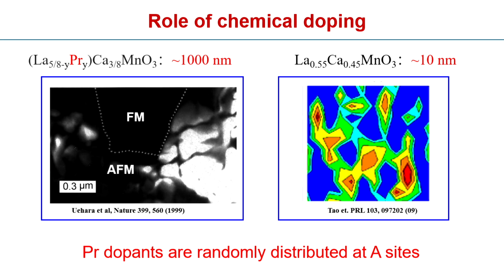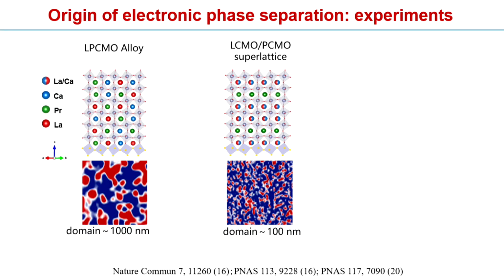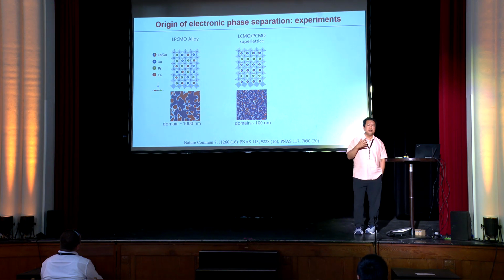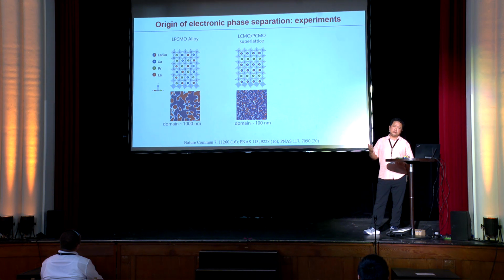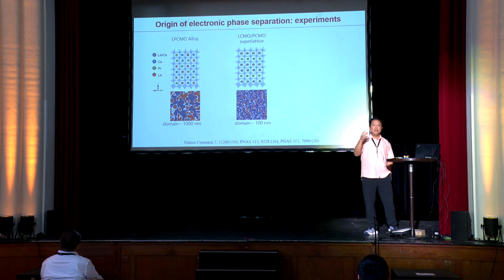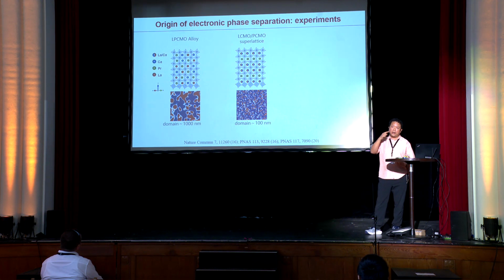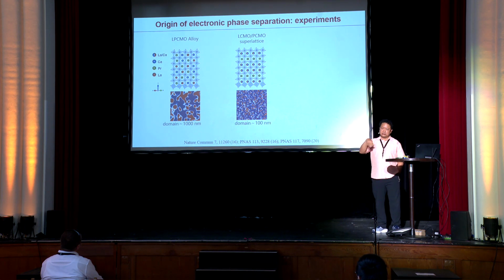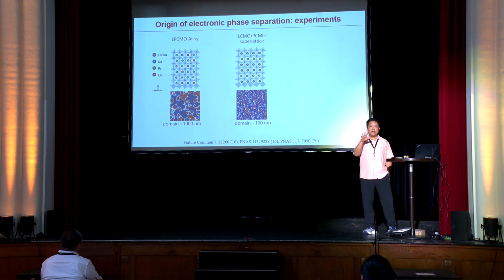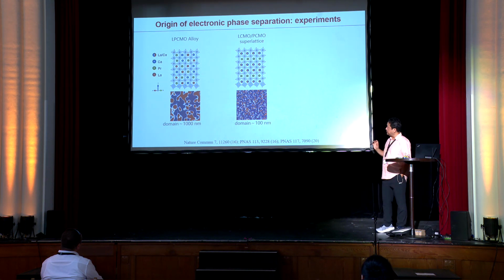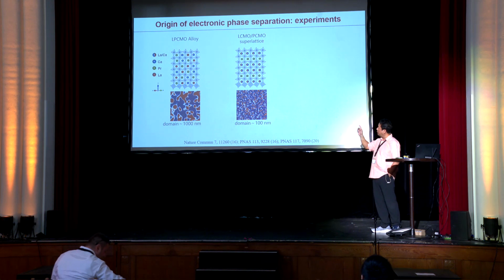However, taking the praseodymium dopants away is too much of an action on the system. So instead we decide to keep the nominal doping concentration of the praseodymium dopants, but just rearrange their spatial location, making it spatially ordered. The way you can do it is by using superlattice growth. You grow two atomic layers of LCMO, the lanthanum calcium manganese O3, and one layer of the praseodymium calcium manganese O3. So you stack this together as a superlattice. You make the nominal doping concentration exactly the same as the conventional LPCMO single crystal thin films, but the praseodymium dopants now become spatially ordered at the A site.